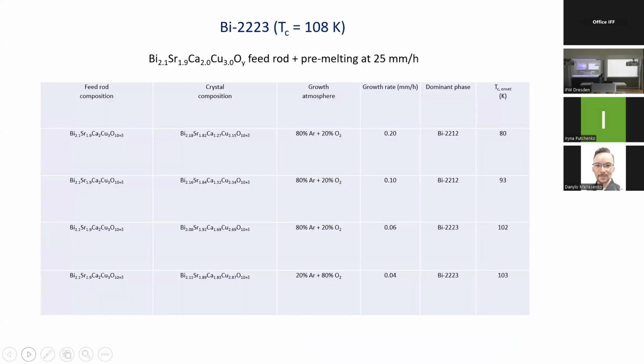So finally, the most hardly grown bismuth 2223 material with the highest Tc in this family. This table shows the growth conditions, and again the most important parameter is the pulling rate. If we use relatively high pulling rates, 0.2 or 0.1 millimeter per hour, even if we use bismuth 2223 composition for the feed rod, nevertheless the major phase is bismuth 2212. And only when we apply extremely low pulling rates, around 0.05 millimeter per hour, could we stabilize the formation